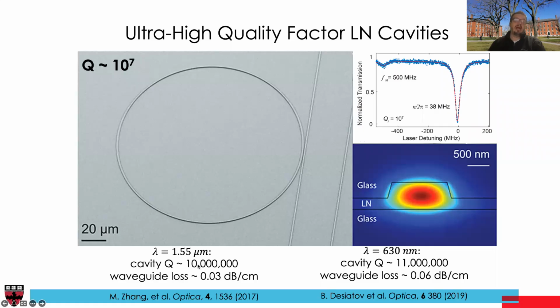So basically, this value that we measure is limited by our fabrication of the material. So there's a lot of opportunity that could be unlocked if we can further increase this quality factor. This quality factor of 10 million, by the way, translates to waveguide losses of about 3 dB per meter, which puts this integrated thin film lithium niobate platform as one of the lowest loss integrated photonics platforms. And importantly, we have demonstrated this in both telecom and visible wavelength range.